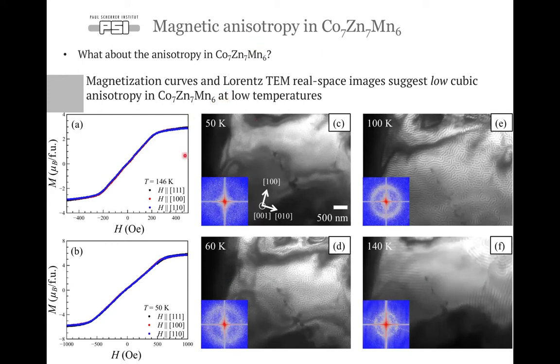We have measured SQUID magnetometry for the 111, 100, and 110 main crystallographic directions. And basically in M-H loops measured at both 146 K, just below the TC, and at low temperature at 50 K, we don't see any difference in the magnetization curves for these principal directions, already suggesting that the magnetic anisotropy in this material is quite weak. It is very isotropic.